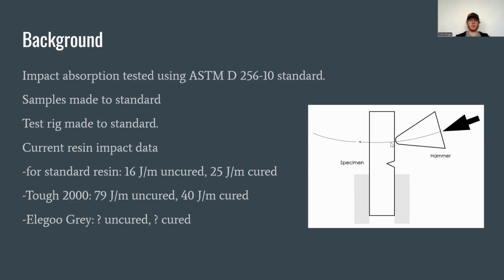For Formlabs black, clear, and white, the average impact energy is 16 joules per meter uncured and 25 joules per meter cured. In our experiment, we only tested black, so we can't verify whether standard resins indeed have the same properties or if pigment significantly changes each resin's impact resistance.